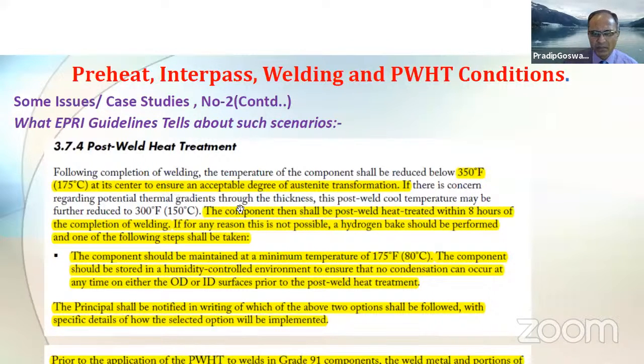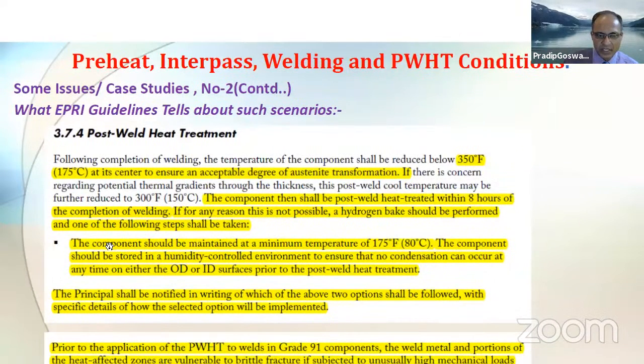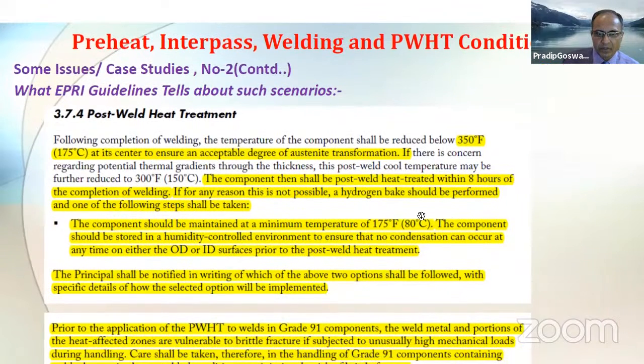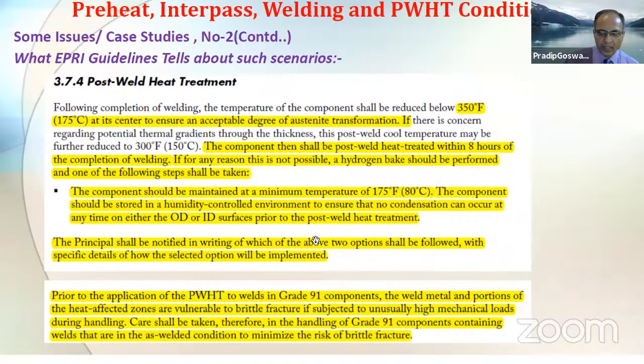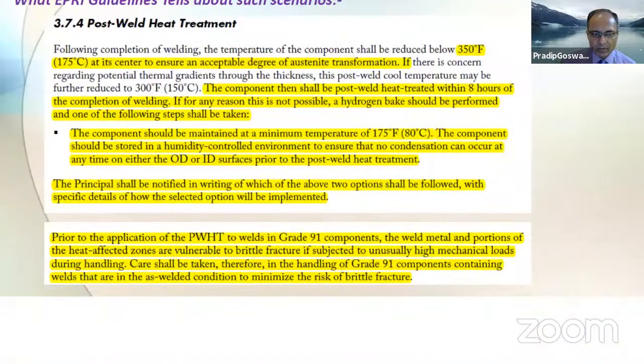Basically, this is with respect to typical case studies, but he says that the critical part is this one. The component shall be maintained at a temperature of 80 degrees centigrade. The component shall be stored in a humidity controlled environment to ensure that no condensation occurs at any time on the OD or ID surface prior to post-weld heat treatment. We'll talk about why it is required.